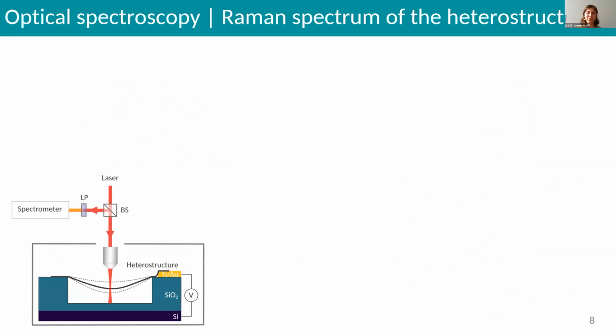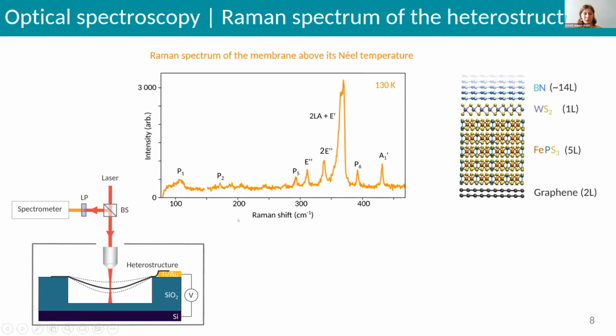And here for FePS3, Raman spectroscopy is the most appropriate tool. Raman spectroscopy uses inelastically scattered light to probe the crystalline vibrations, so the phonons. For this, we focus the light on the heterostructure, and we recover the scattered light on the spectrometer using a long-pass filter. So we obtain such a spectrum. Each peak of the spectrum represents a vibrational mode of the atoms in the crystal.